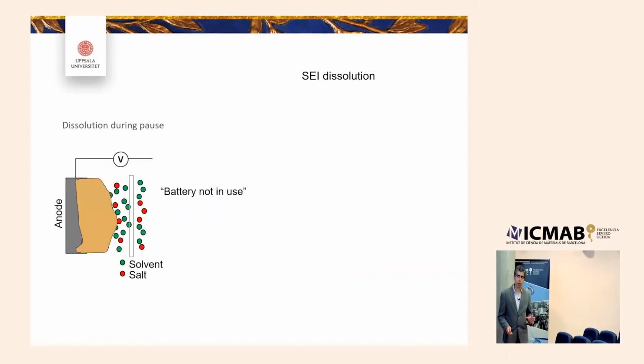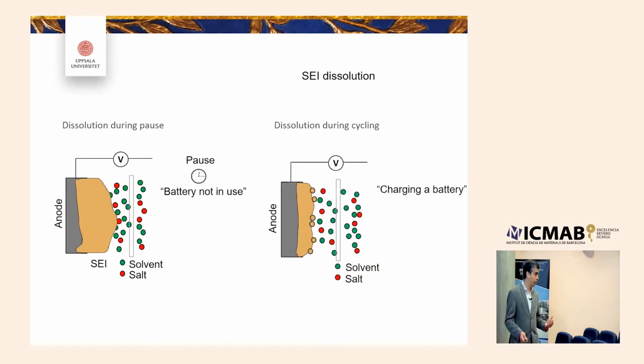This SEI should be stable, as I said, but when you stop the battery, what can happen is that the SEI may dissolve back into the electrolyte. That's a problem because it means you need to reform the SEI again if it's not passivating. The same thing can happen when the battery is in performance—discharging or charging—and this SEI dissolution may cause capacity fading.